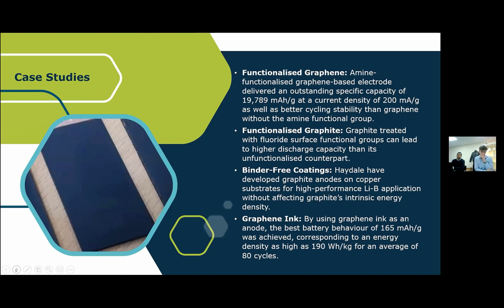And some case studies basically to show how our material can be beneficial for the batteries and supercapacitor industries. Starting with functionalized graphene, we have demonstrated our amine functionalized graphene basically improves the specific capacity of batteries by 19,000 milliamp hour per gram at a current density of 200 milliamp per gram. And it also improves the cyclability of the system as well.